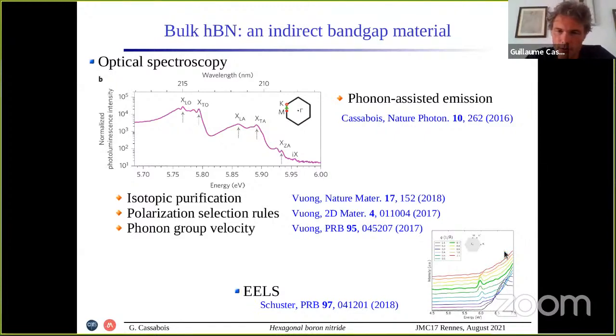I would like to mention this completely complementary study performed by electron energy loss spectroscopy by our colleagues in Dresden. The main difference between optical spectroscopy and electron spectroscopy is that electrons can carry a momentum high enough to directly excite the exciton. In the case of photons, it's not possible because the wavelength of light is too large compared to the atomic distance. But our colleagues managed to really map the excitonic dispersion, and they found the indirect exciton in the middle of the gamma K line, exactly as we had found from optical spectroscopy.